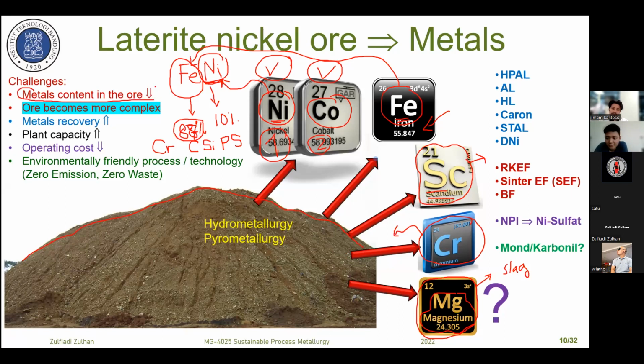What you see here, the valuable metal content in the ore tends to decrease. For example, here, the nickel content sent to the smelters in the last 20 or 30 years was more than 2%. But now the nickel content is around 1.8, or even in one plant, they have designed the RKEF plant to process nickel ore with a nickel content of around 1.6%. That is the current situation.